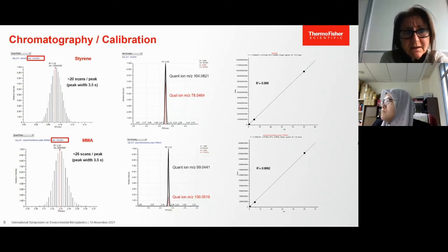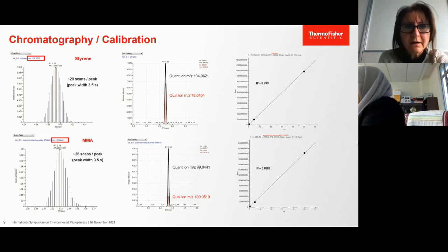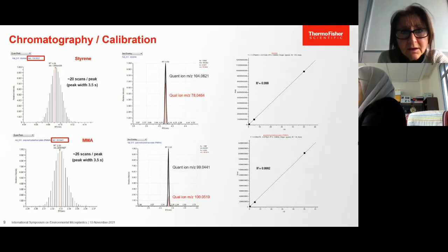On the left-hand side of the slide, you can see the number of scans per peak exceeding 20 scans for a 3.5-second wide peak, allowing for an accurate peak integration and compound quantification. Excellent linearity responses were also obtained for both compounds with a correlation coefficient higher than 0.999, and the percentage relative standard deviation of the response factors was below 15%.